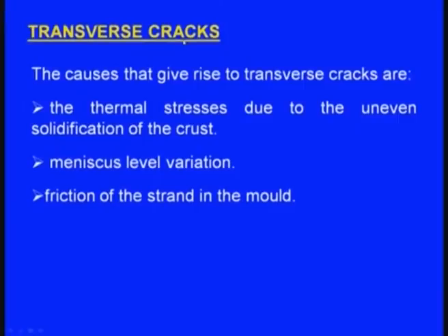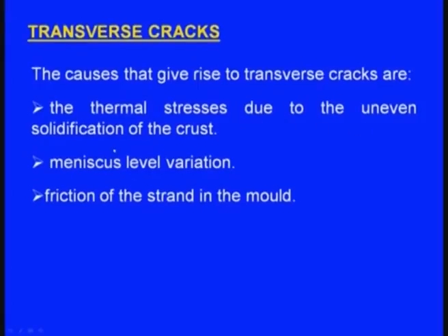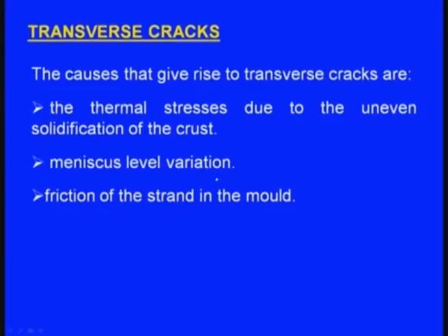Next one, let us see the transverse cracks. These transverse cracks are due to the following. The thermal stresses due to the uneven solidification of the crust. Next one, meniscus level variation. Next one, friction of the strand in the mold. So, all these contribute to the formation of the transverse cracks.